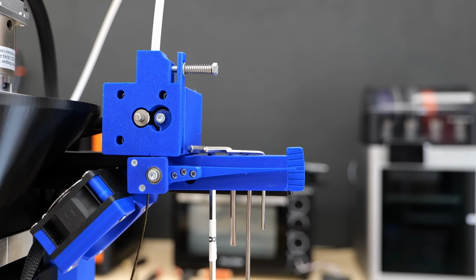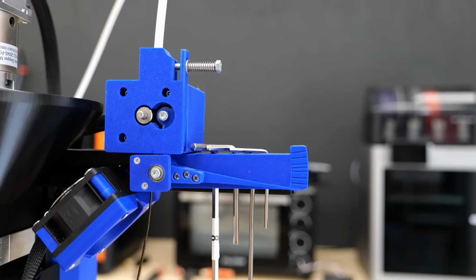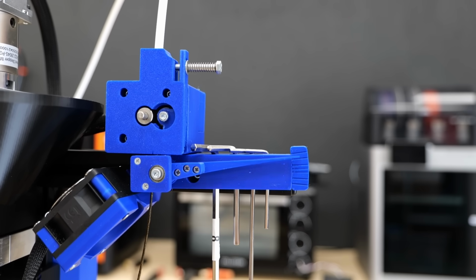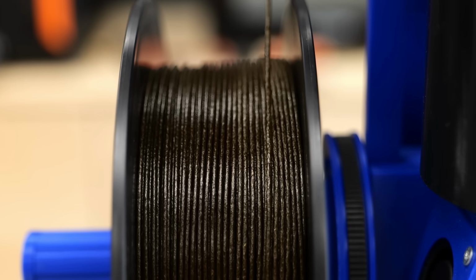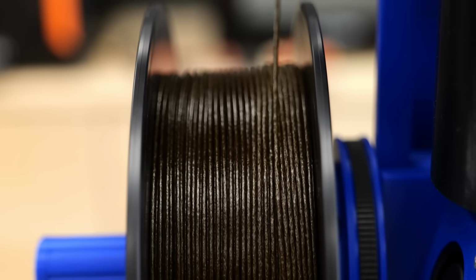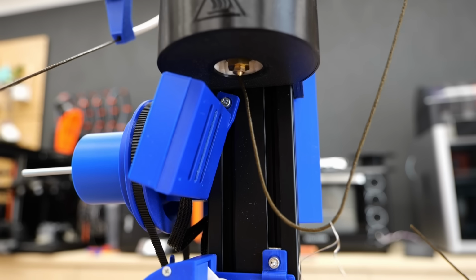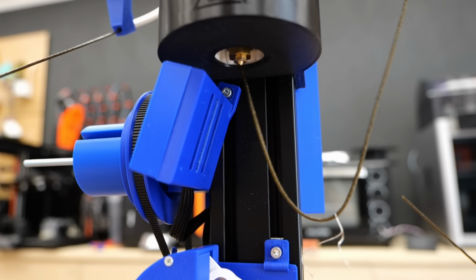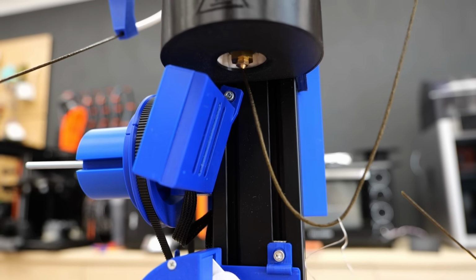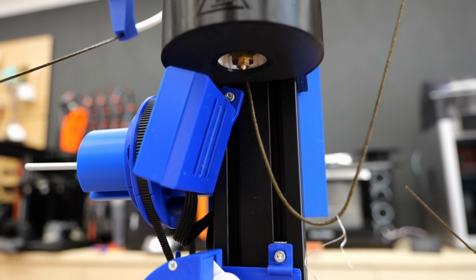Unfortunately, after about half of the material was extruded, I started noticing that the diameter fluctuated quite a bit and also the color of the material changed from a dark brown to a lighter hue. This quickly became worse and I realized that the filament was actually foaming up once it left the nozzle. I'm still not sure about the reason behind this.